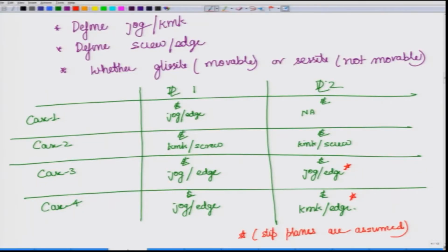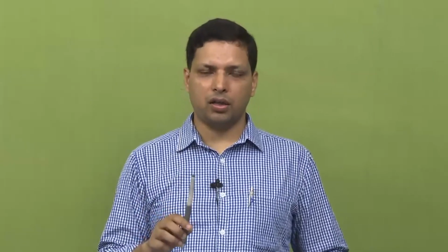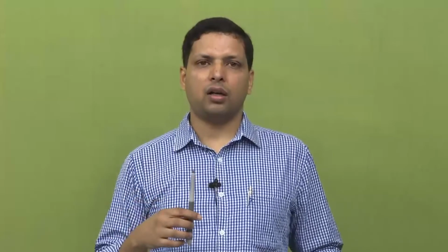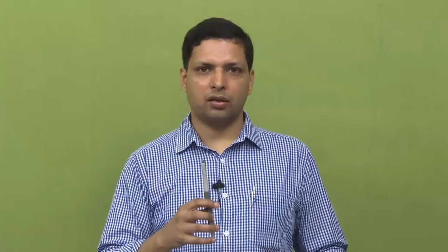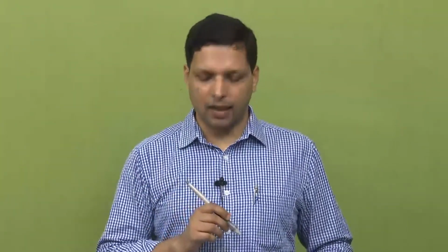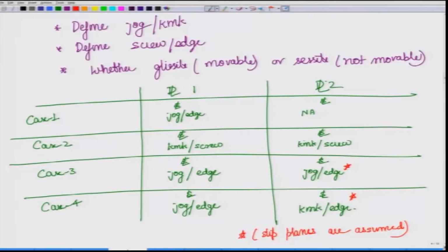And what is that? The one when we have a jog. When a jog is formed, it forms an edge dislocation which remains confined to a particular plane, and then it cannot move in the same direction as the slip direction, and therefore it pins down the dislocation, and therefore it is a sessile dislocation or a sessile character. It is sessile in nature.